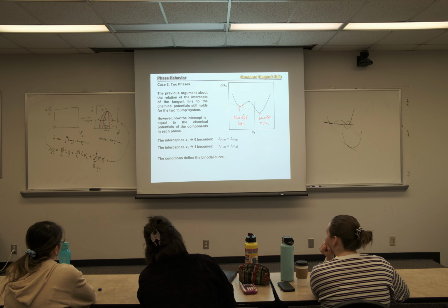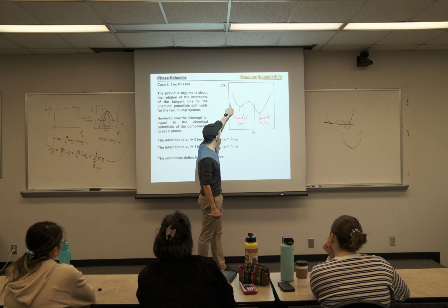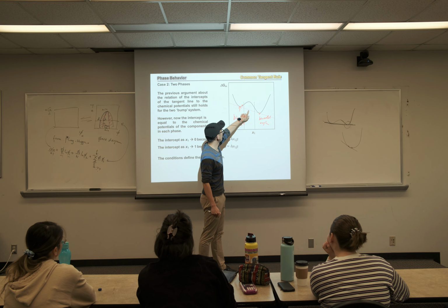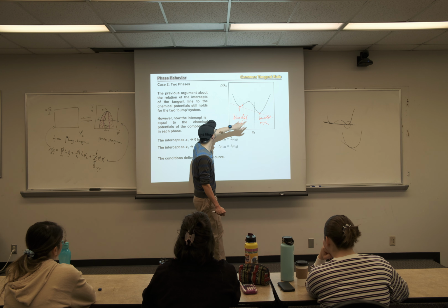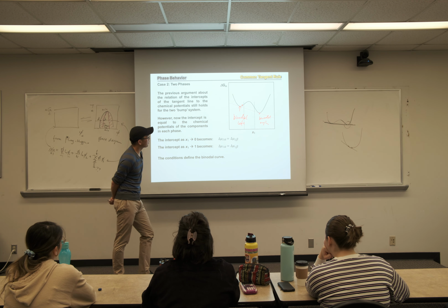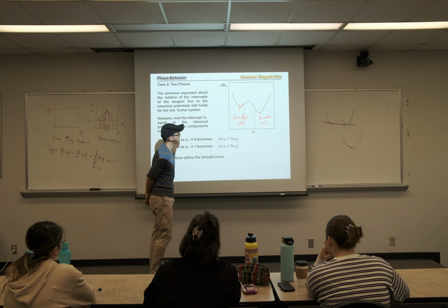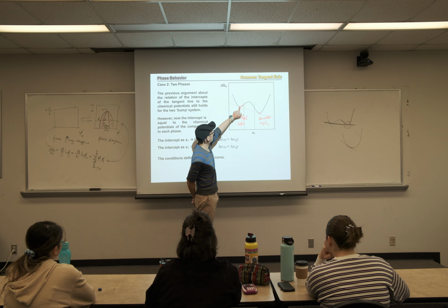So this is just one line, and in the next slides, we will show you this would be the line that defines the same chemical potentials for the whole system. So this would define the lowest chemical potential, this particular red line, okay? That's what we call the tangent line intercept with our system. So in this intercept, your polymer's chemical potential will match from here and there. It's in a relatively stable state. So this point defines the binodal. This defines spinodal, where the second derivative equals 0, and the lowest energy or tangent line defines the other boundary condition.